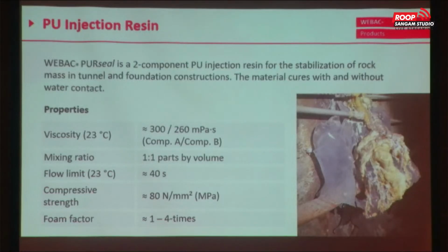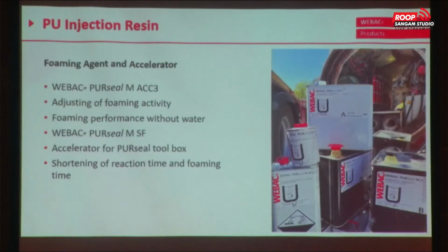pumps. The foam factor is slightly between 1 and 4. This is totally enough to use that kind of material as a water stopper. The important thing is 80 Newton per square millimeter, of course without any foaming. That means this material can be used for anchoring as well, or for soil structure stabilization or slab lifting, which is in each mouth the last years. But compressive strength development is a big advantage of this product.